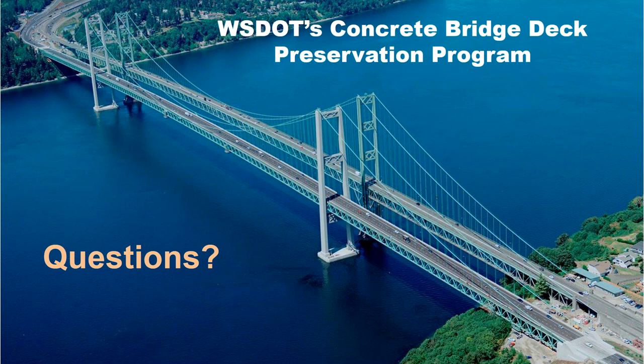Okay, next question is, how common is rutting on bridge decks? It depends on where you're at. If you're in Spokane, the answer is very common. Spokane, because of the nature of studded tires and the culture, will get about 1-inch ruts after about 20 years. And so on the main Spokane viaduct, which is I-90 through Spokane, you'll start to see rutting there. We see rutting up on Snoqualmie Pass, the mountain passes, where you use a lot of studs and chains. So it becomes a lot more common as a bridge gets to about 25, 30 years old, and overlays the same thing. We're starting to see more rutting because we don't have the funds to do rehabilitation as often as we would like. So I think it's going to become more common, especially on the eastern side and in Spokane.